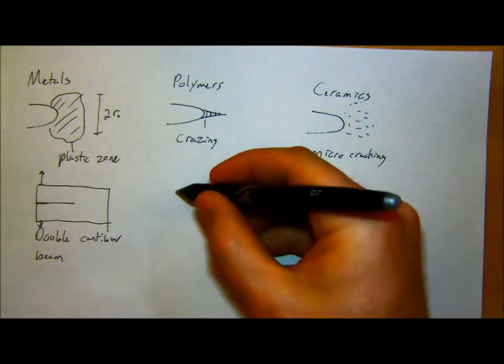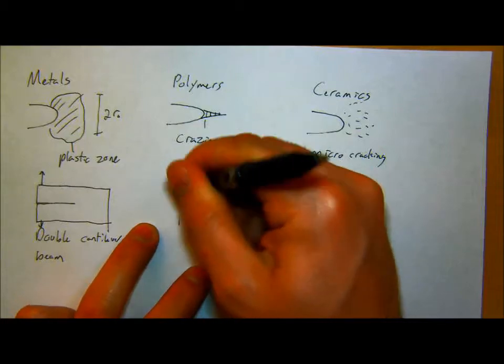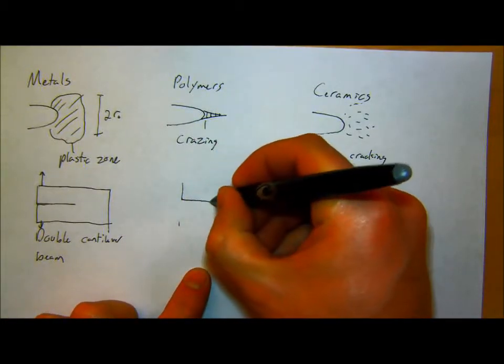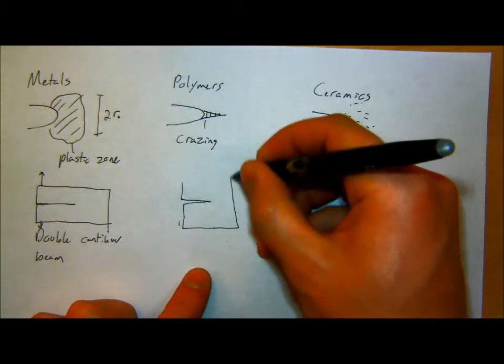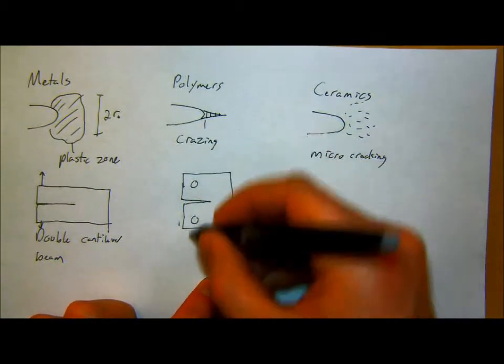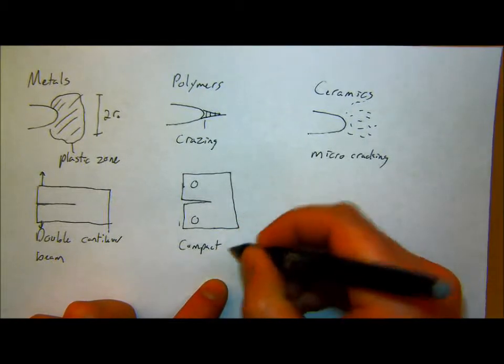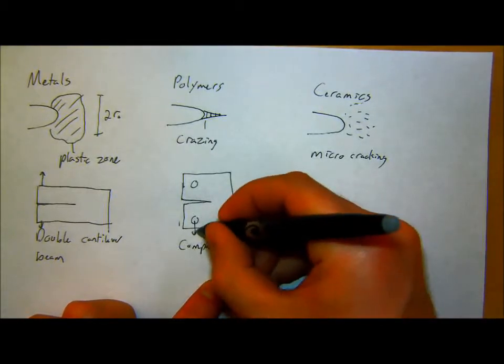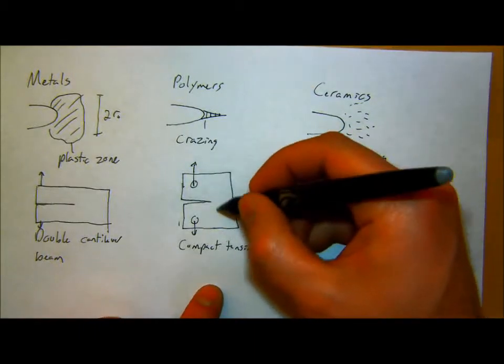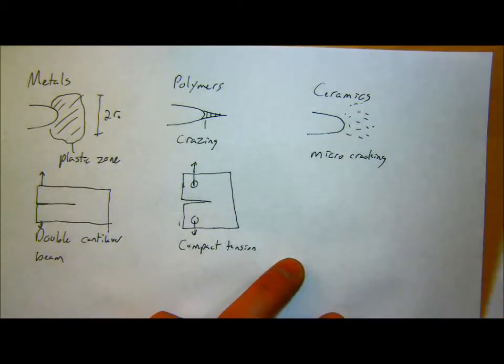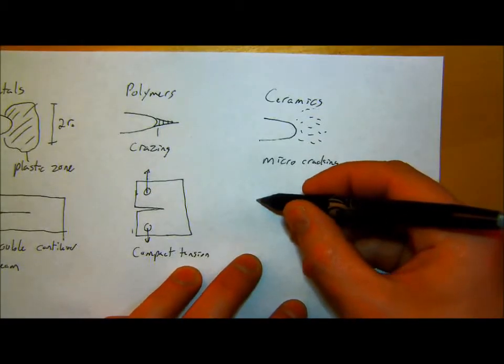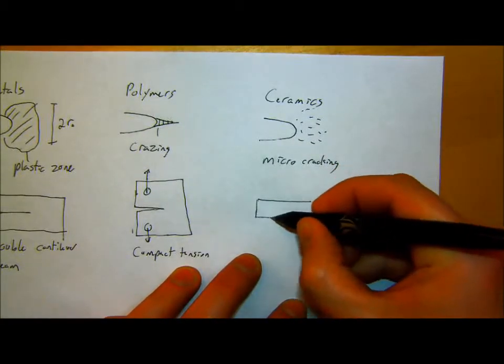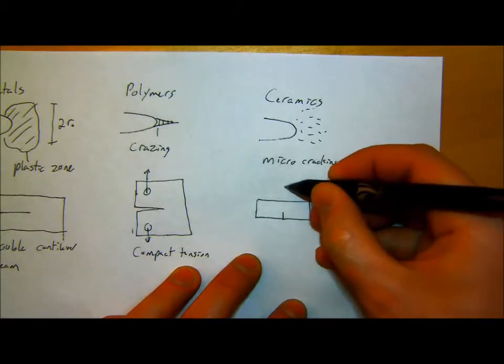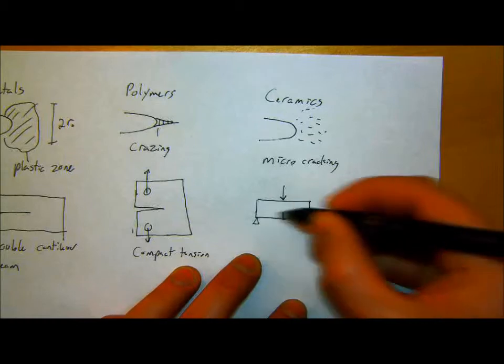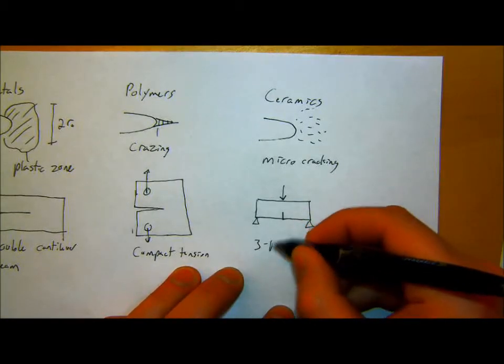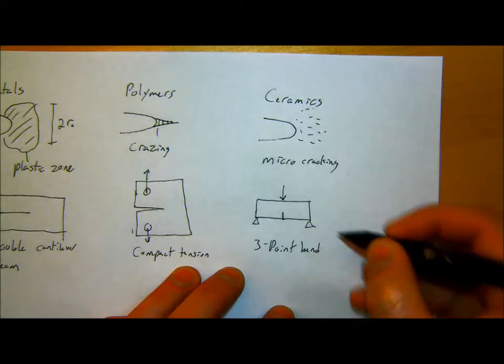Compact tension specimen, where you drill holes and you pull on those holes to cause a stress around here. There's a bending test, which is sort of what you're doing in the Charpy test, except maybe with not a sharp crack. If I apply a force to a beam, so 3-point bend, then I'm getting a tensile force around the tip of this, and that'll cause that to propagate through your material. So there's a few different ways experimentally to test the fracture toughness.